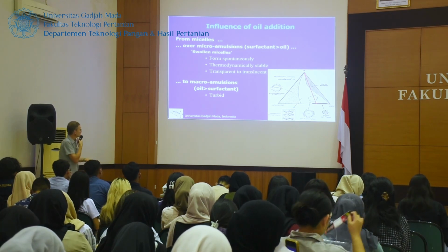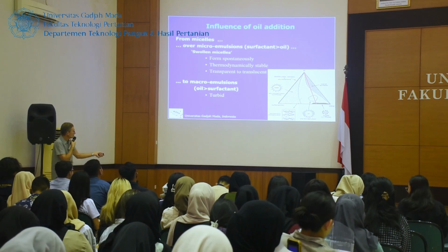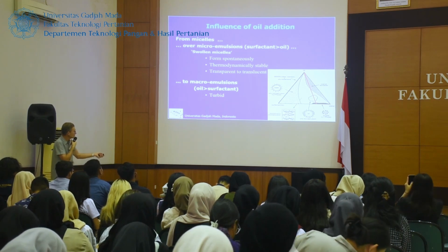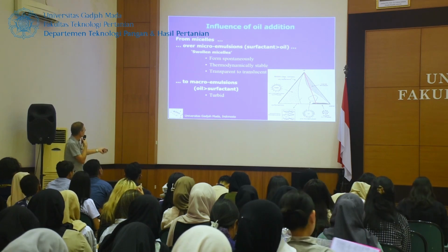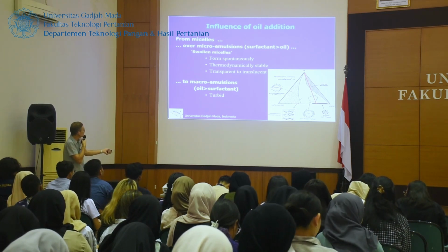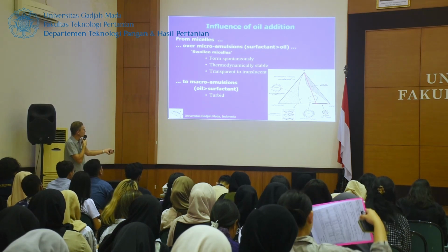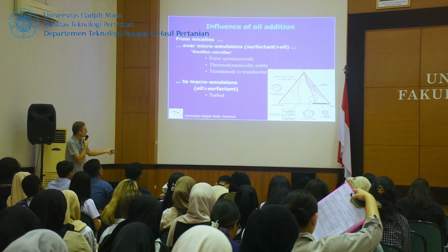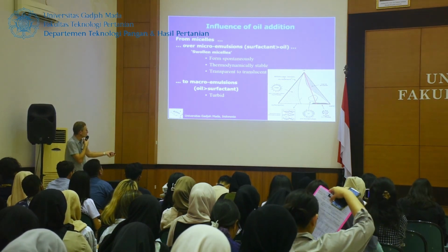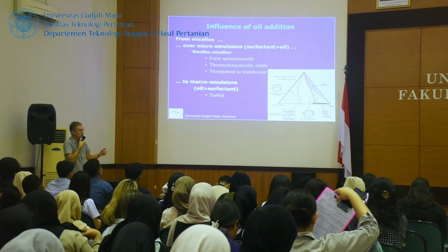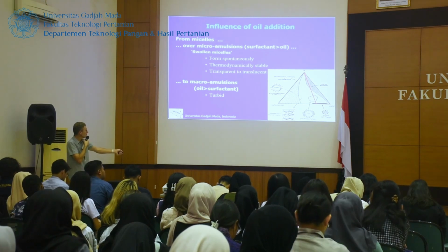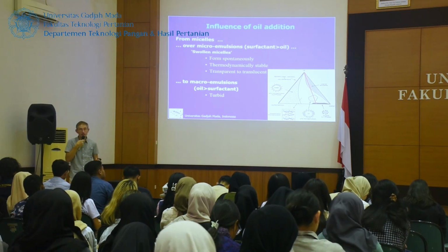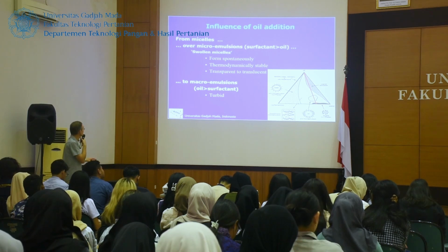What we know then is that if you add oil, it can be taken up by your micelles here. And so what will happen then is that as you add oil, you go from pure micelles to micelles that include quite some oil. Then we talk about swollen micelles. So here we have micelles of a couple of nanometers, and this kind of swollen micelle can typically be some tens of nanometers.